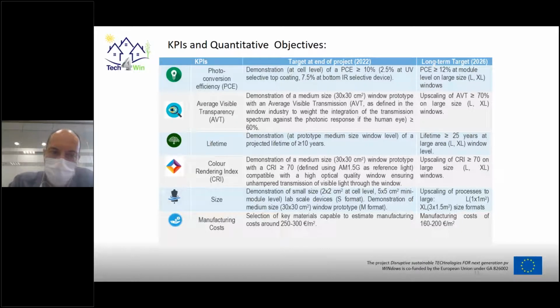We need also to have a very high optical quality. We want to be sure that windows are really transparent in the visible and don't have any kind of coloring effect. So they have to be color neutral. This we are measuring by the color rendering index. We want to demonstrate in the prototypes a value of the CRI, the color rendering index, higher than 70, which corresponds to a high optical quality window, and so ensuring unhampered transmission of the visible light through the window.